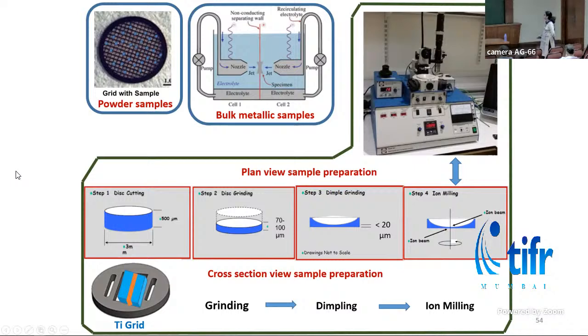TEM sample preparation is a very tedious job, and you can imagine at every stage we have to handle a sample which is 100 micron thick. So this really needs a skill, and sample preparation can take as long as 3 to 4 days because the ion milling times depend on the sample, and they can be as long as 6 hours to 8 hours. So Jayesh does that job very sincerely for us. That's why we can get very good TEM samples.